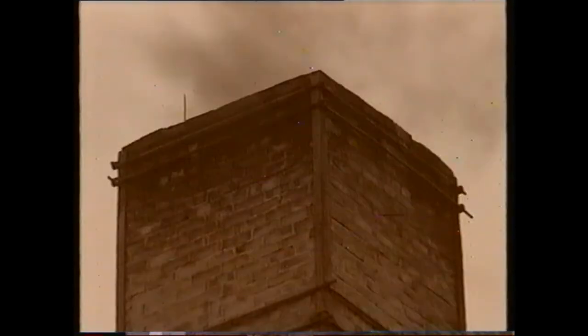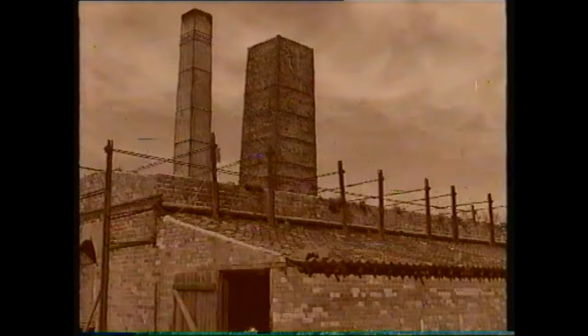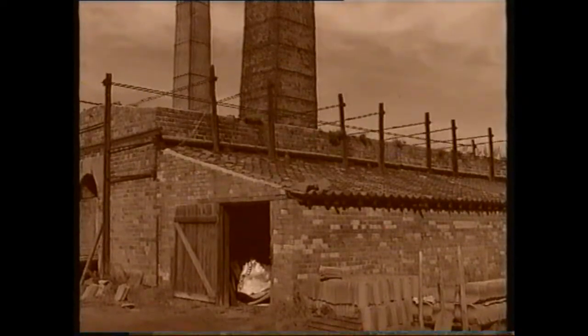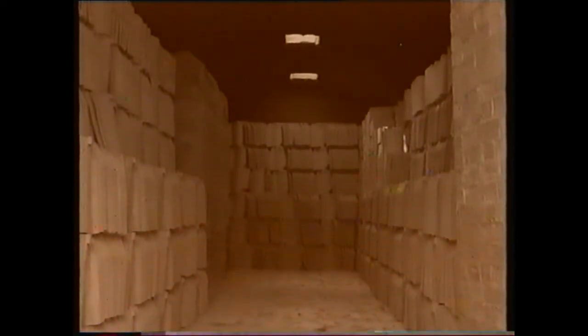There were peepholes around the kiln, but you couldn't really see that much through them. Sometimes you could tell what the state of the burn was by looking at how much smoke and steam was coming out of the chimney. All day Tuesday the fires were kept up high, until sometime on Wednesday when, if it was reckoned that the tiles were ready, bricks would be put on top of the fire and it would be covered over with pug to dampen down and stop any air getting in. The kiln would be left to cool until the following Saturday, when we'd unbrick the doors and take all the tiles out and start the whole thing over again. Men would be known as good tile burners for their skill at knowing just when the tiles would be ready — my grandfather was well known hereabouts as a good tile burner, and he was very proud of it too.